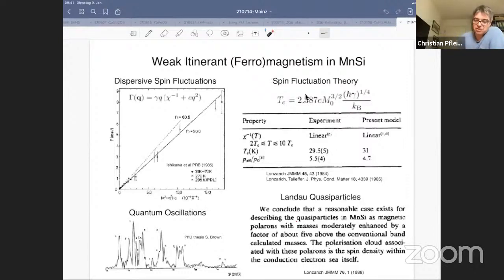Very brief introduction to MnSi. It has a very, very long history. It was studied in the 80s as a weak itinerant ferromagnet. That's not really ferromagnetic, but it's ferromagnetic enough. So there was a lot of interest in the ordering. At 30 Kelvin it undergoes a phase transition from a paramagnet to a helimagnet, with a long wavelength helimagnetic modulation. When you apply a small field, you get a spin-polarized ferromagnet.